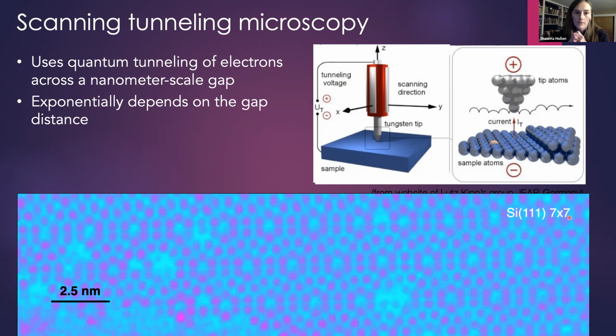And this is actually one of the first big mysteries that STM was able to solve, because before the invention of the scanning tunneling microscope, we were only using diffraction to see atomic surfaces, which is a much more complicated technique, and you don't get real space images. So people didn't know what this special reconstruction was. And when they imaged it with an STM, it was like a revelation. Oh my gosh, this is the pattern we've been seeing in this other tool that we couldn't interpret.